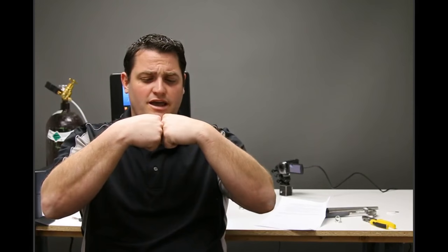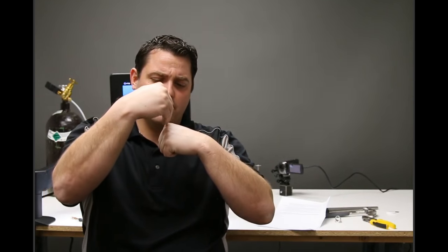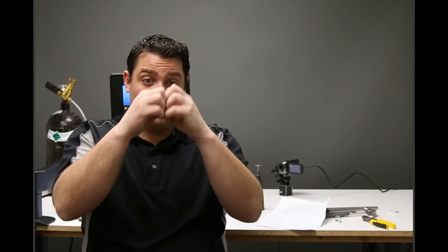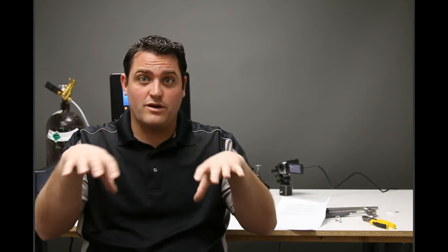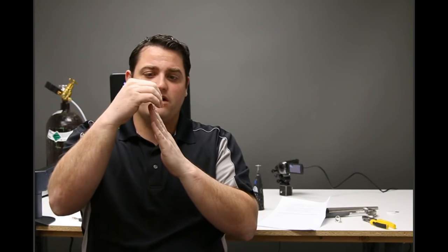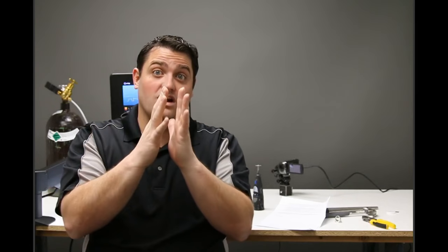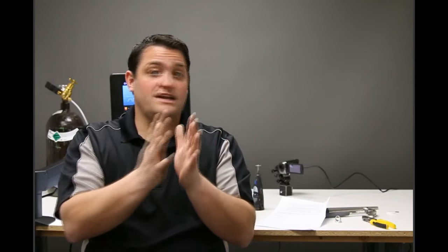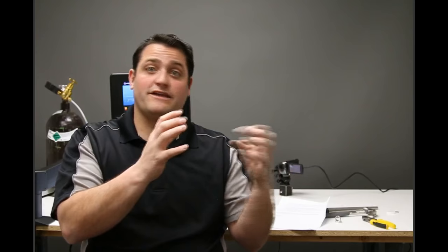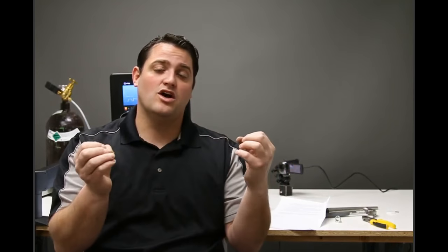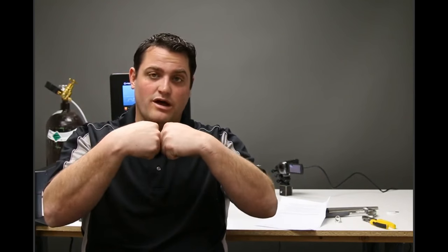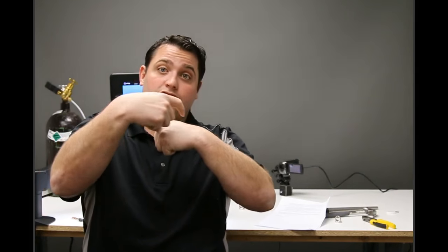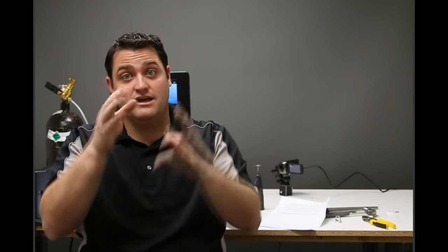And so what happens is we create that joint and we're welding across the top here, the energy is flowing really, really quickly away from it. You don't get very far into that joint before it's completely cold. It wasn't even affected by the weld because it wicked the heat away so fast. It pulled it away from the weld site. So one of the ways to alleviate that is to anneal not only the specific weld site, but also further away from that edge on both sides.